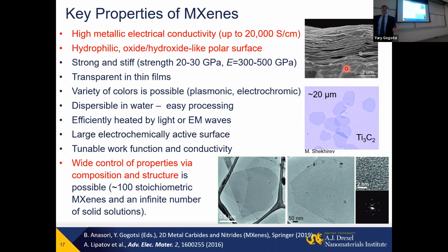Now, it's all great, but it is only useful if this material brings something new to the table, because if you already have clay and clay can do everything a new material can do, why not use clay or even graphene, which have definitely been explored to a much larger extent. So let's look at the properties. I already mentioned conductivity. For example, you can see here a multilayer film of titanium carbide, and we get up to 20,000 Siemens per centimeter just by vacuum-assisted filtration, or spreading it over the surface, or spray coating. For people who are familiar with graphene, if you take, for example, a film of reduced graphene oxide, which will look in a very similar way, the maximum value you will get is 2,000 to 4,000 Siemens per centimeter. So we get already an order of magnitude higher electronic conductivity.